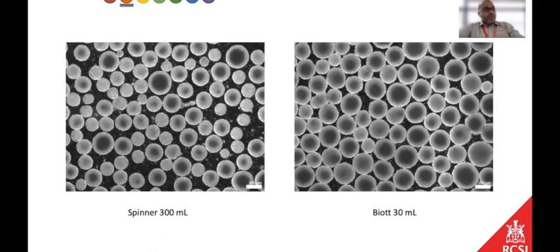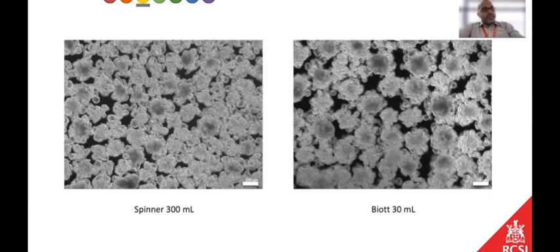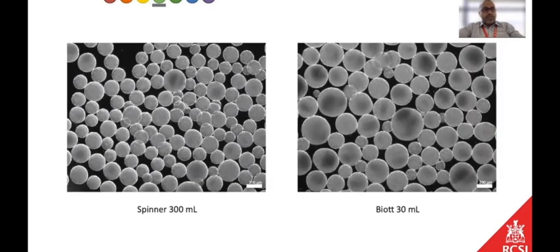In the next one, at stage 3, day 1, they attain this kind of popcorn-like morphology. The Melton lab at Harvard calls it flowering, but to me they more resemble popcorn. But irrespective of what you call them, the morphology of the clusters looks like this. And then after 2 days, surprisingly, they just get back to the spherical shape. And this is very, very amazing. If they don't get back to this spherical shape in this early pancreatic progenitor stage, there's something going wrong with the protocol. So you have to go back again and start all over again.